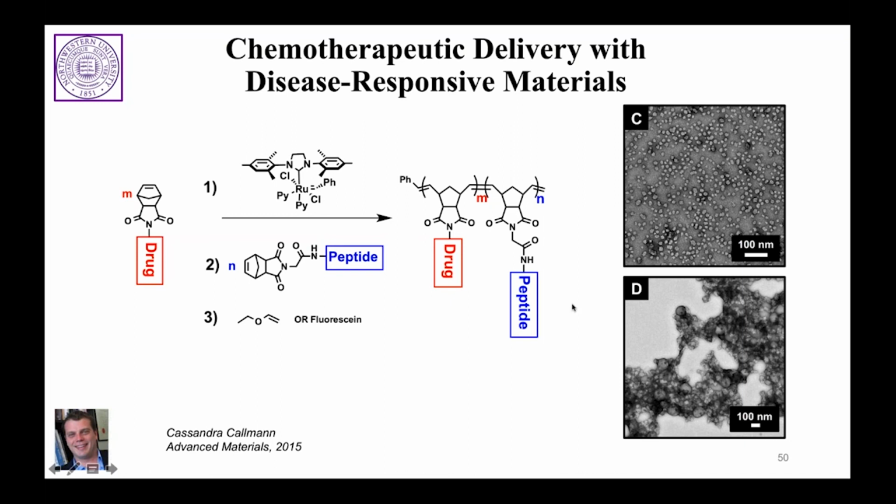As the peptide gets depleted, you decrease the size of that polar head group and you get an aggregation event. Now, this is actually a true change in the nature of the particle itself. It exposes the drug and then the drug begins to leak. And so you've tied together the ability for us to form this aggregate, this kind of implantation event following intravenous injection, with a drug leakage profile.